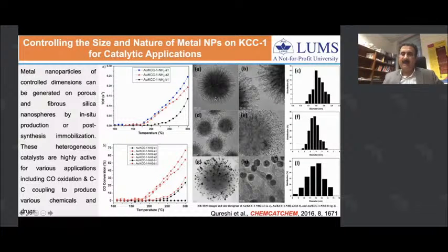What we did is we functionalized this silica nanospheres with amine groups, and then generated very small clusters of gold, which are 1 to 2 nanometer, and then in another case gold particles 4 to 6 nanometers, and then 10 to 15 nanometer gold nanoparticles. We tried to figure out how the size of these gold particles affects the catalytic properties of these kind of heterogeneous catalysts.